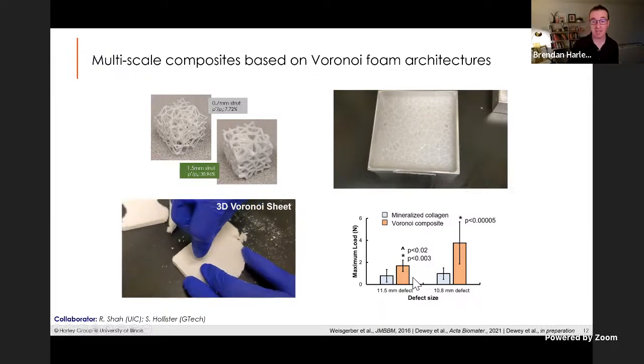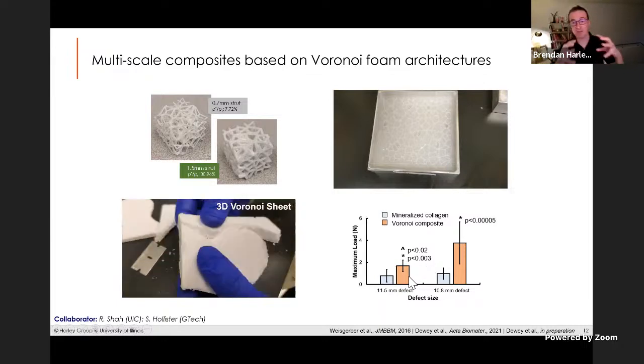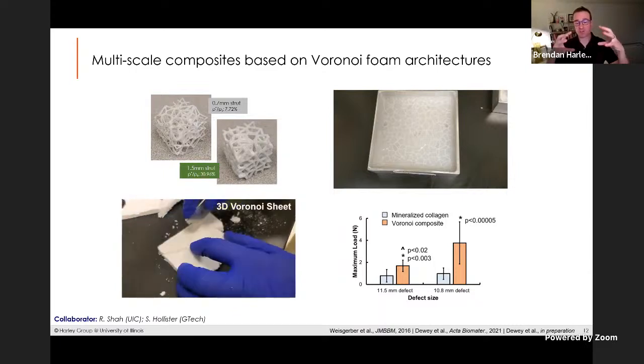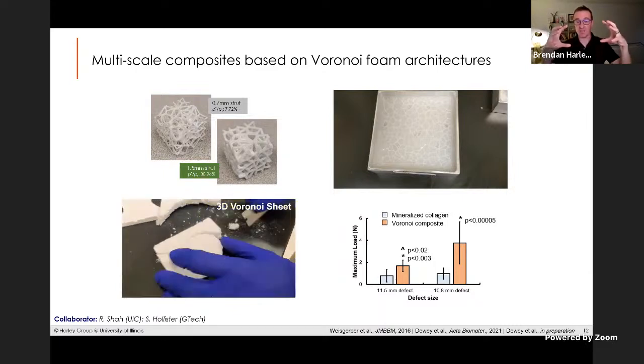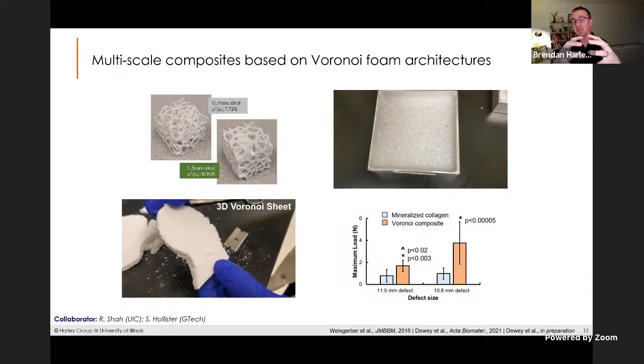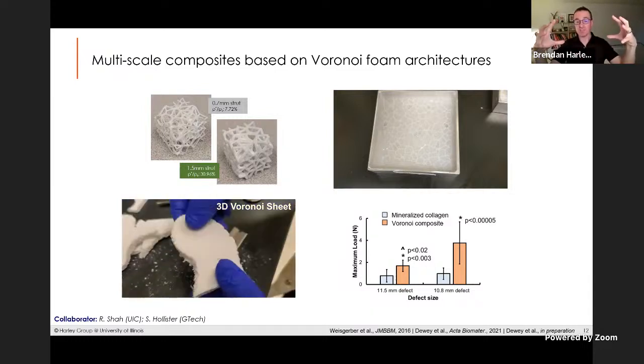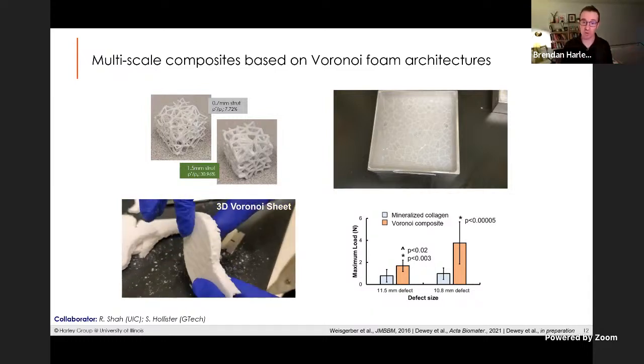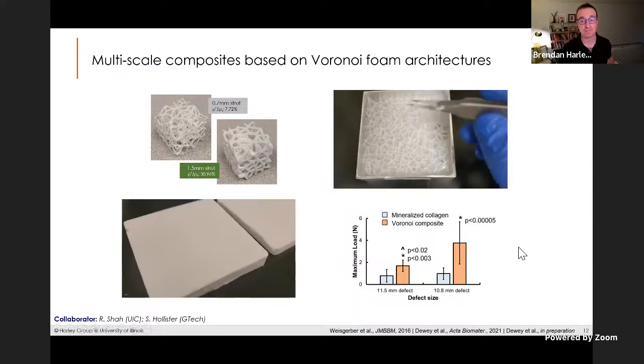And one of them is what's known as compressive strength. And so these materials, now our surgeon can cut it to be slightly larger than the defect. They can squeeze it, put it into the defect, and it springs back and fills the shape. So that means we get really nice conformal fitting and a strong implant that supports bone growth. So we're really excited about getting this into clinical trials over the next couple of years, where you have a material that's really exceptional for bone healing and a mechanism by which surgeons can handle it and cut it and shape it to fit all the different types of defects that they're faced with at a clinical scale.